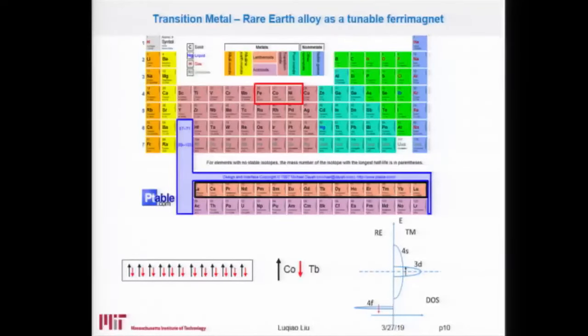Okay, so what kind of system can we utilize in real life to realize such kind of property? So here, actually, we utilize this kind of alloy system that has been studied for quite a long time, which is a transition metal rare earth alloy. Just to give you an idea where those elements are located in the periodic table, for transition metals, we are talking about those three elements, iron, cobalt, nickel, because those are the most traditional ferromagnetic elements. And then for rare earths, we are talking about elements that are located here. And particularly today, we are talking about terbium, which is this 4F rare earth element.